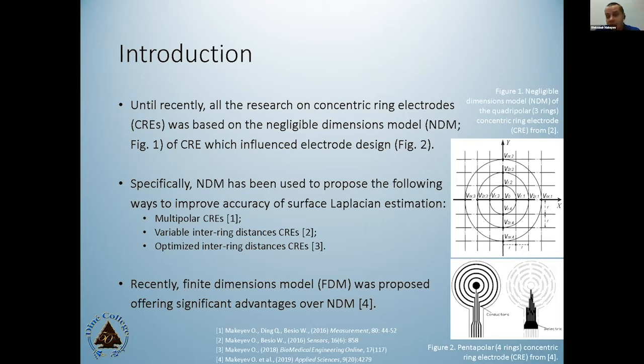Then we realized all the models so far have been used with equal distancing between the rings. So what will happen if we change the inter-ring distances? We played with that. We realized that positioning the rings first really close to the center and then further and further and further out at increasing distances allows you also to increase the accuracy of the Laplacian signal. And last but not the least, we solved the actual inter-ring distances optimization problem, which resulted in those kind of obscure optimal ranges as to where you can place each of the rings to obtain the 5th percentile of the error, 95th percentile of the possible accuracy.